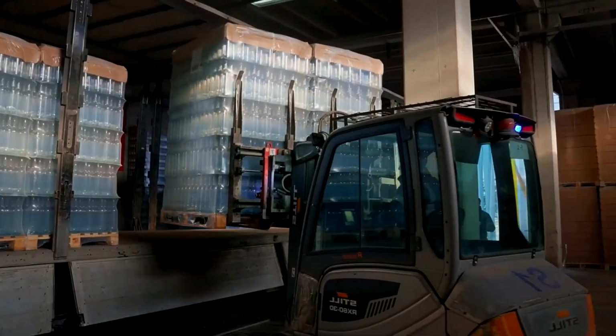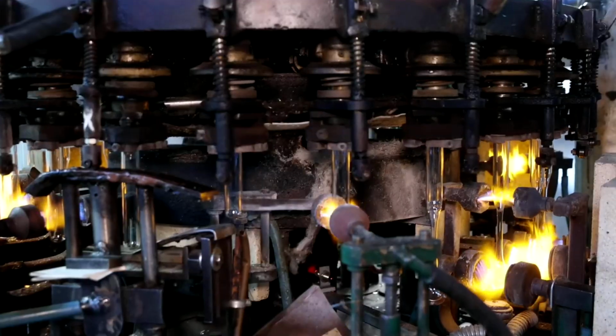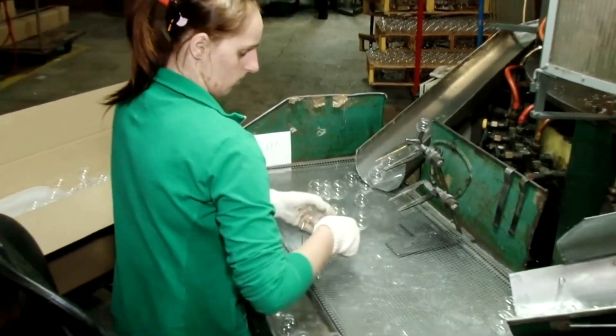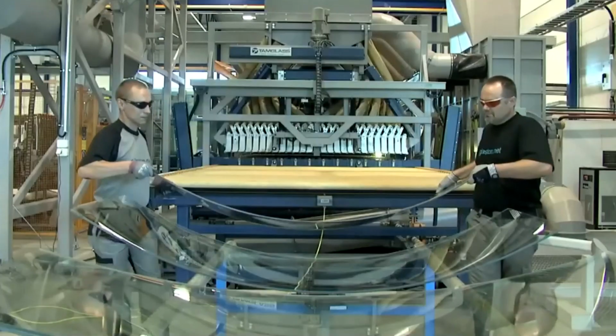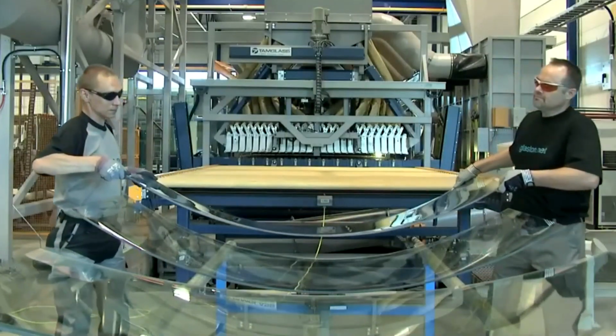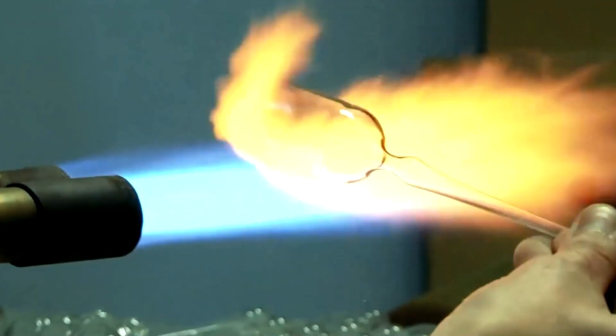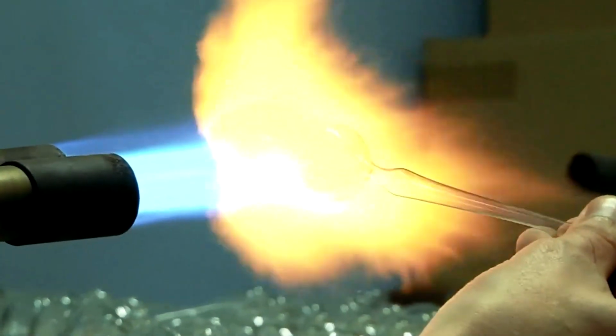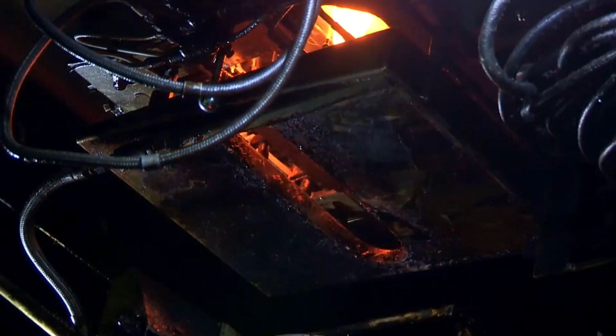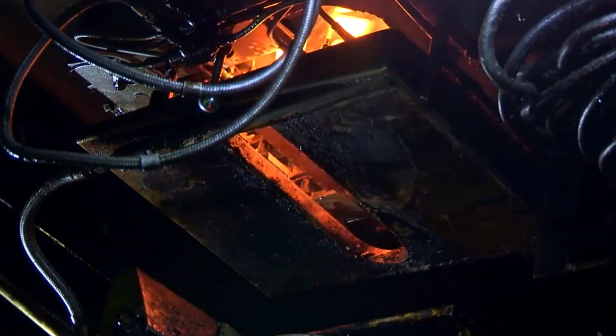products, including automotive windshields. The mixture for automotive glass melts and flows into a bath of molten tin at temperatures ranging from 1,800 to 2,000 degrees Fahrenheit. Since glass is lighter than tin, it floats on the surface, spreading into a continuous ribbon. The equipment gradually stretches the ribbon using edge rollers to control the thickness and width. The liquid interface ensures the glass becomes perfectly flat, eliminating optical distortions.